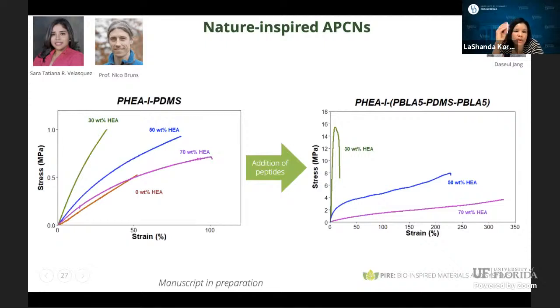You have some diversity in the overall strain, some changes in the moduli, but when you add our peptide structures, so these are PDMS, PBLA5, so these are beta sheet structures, you have a wide range of mechanical properties. So now you can have much higher moduli, and then also some very nice extensibilities up over 300% in these systems. We're preparing a manuscript on this, and this really is due to the interactions that you can have between phases as you add in more and more of the peptide structures.